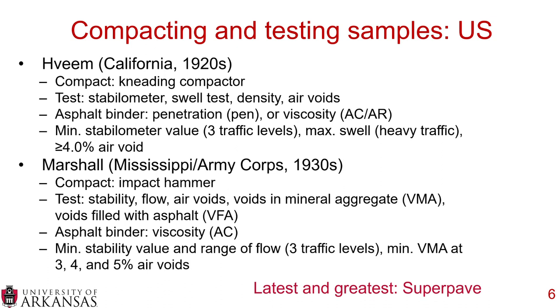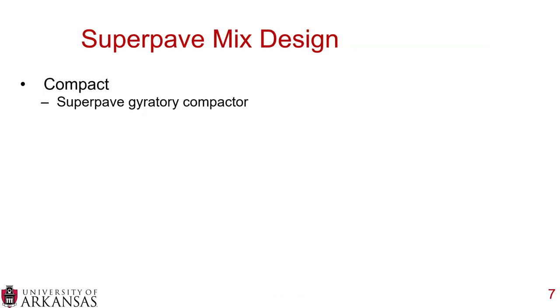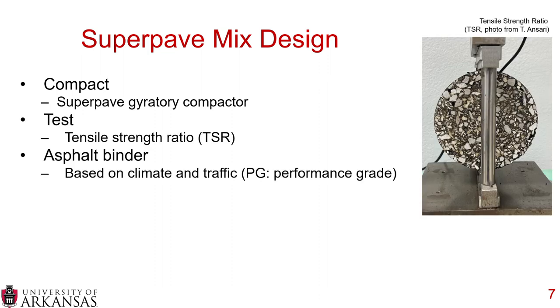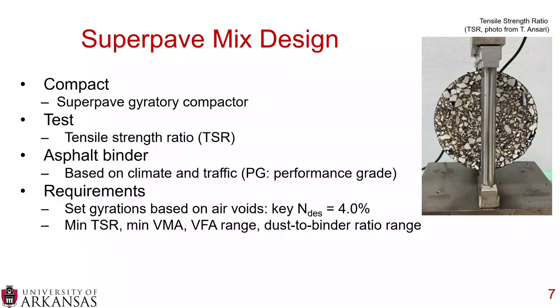Now, the latest and greatest here in the United States is the Superpave mix design system. And you compact samples using a Superpave gyratory compactor. You test them using the tensile strength ratio, and you can see a picture of the tensile strength ratio on the right. The asphalt binder is based on climate and traffic, and we use the PG binder grading system. That PG stands for performance grade. And the requirements is that you set gyrations based on air voids, and the key is putting your N design at 4%. There's also an N initial and N max. And you're looking for a minimum TSR, a minimum VMA. There is a range of VFA you're shooting for, and there's a dust to binder ratio range as well.